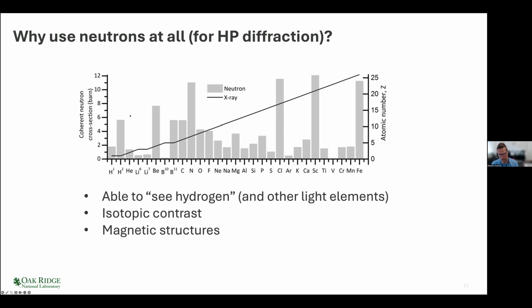When people say neutrons are able to see hydrogen, normally in the case of diffraction, they're talking about deuterium. So actually that isn't hydrogen, it's an isotope of hydrogen with double the mass of hydrogen. So it is a slightly different thing, and I'll return to that later. But you can play tricks with how there's this pseudo random variation of scattering strength for neutrons across the periodic table. So you can look at isotopic contrast, and for geoscience, this manganese iron one is quite useful. These scatter very differently for neutrons, but they have almost the same atomic number, so they're hard to resolve with X-rays. And then famously, because the neutron itself has a magnetic moment, it scatters from magnetic structures.